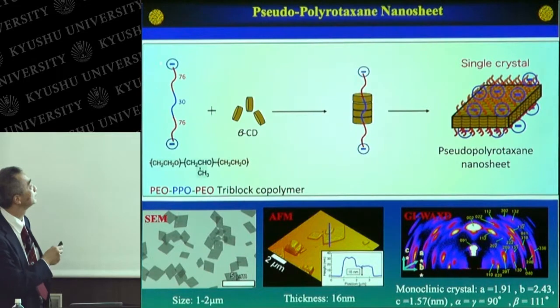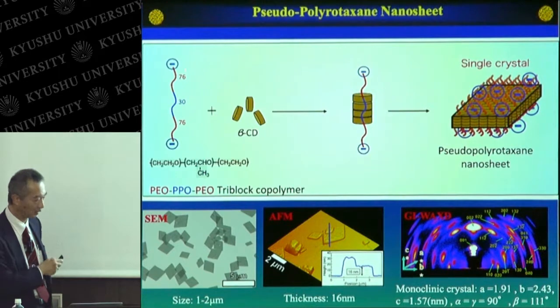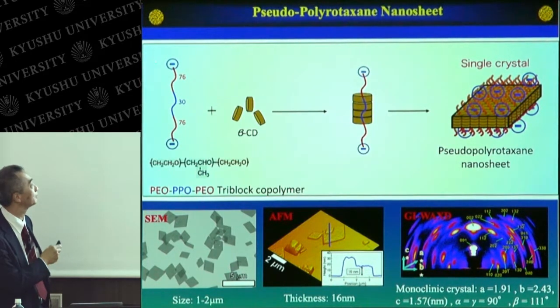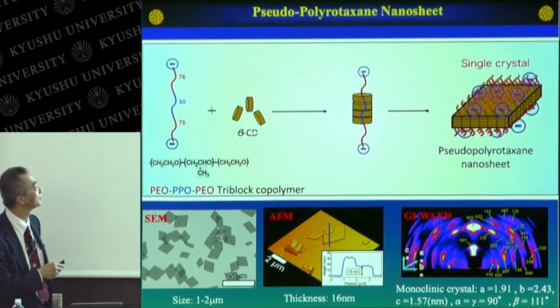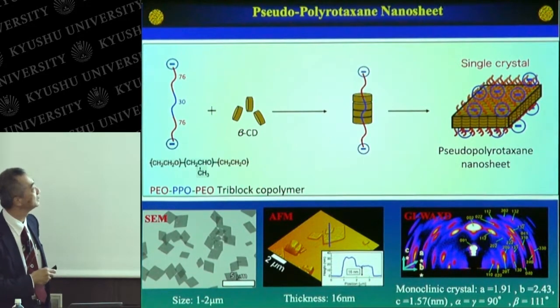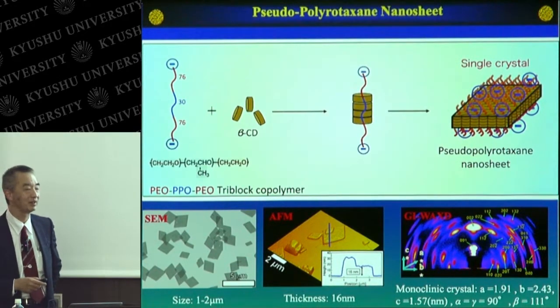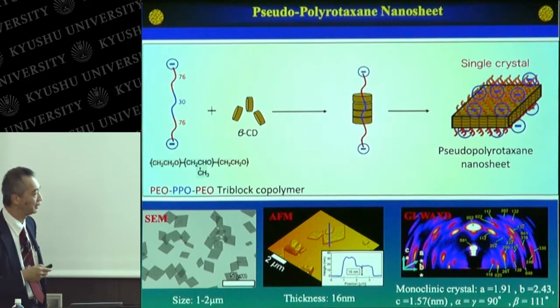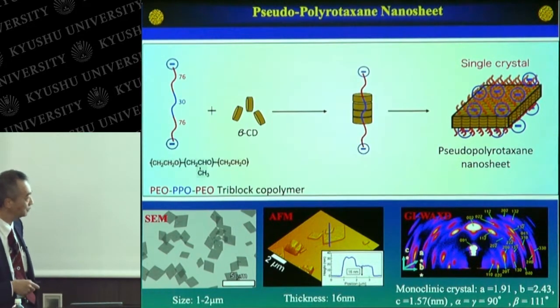And recently we developed a new nanosheet using the polyrotaxane system. We use this 3-block polymer having ionic carboxyl groups at both ends. And we mix this and beta cyclodextrin in water. Then the beta cyclodextrin forms an inclusion complex only with the polypropylene glycol component of the 3-block polymer. Then they form this self-assembling nanosheet, a very robust, simple system.